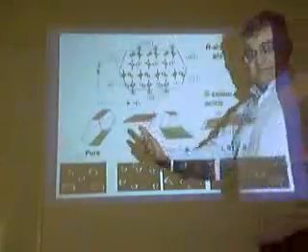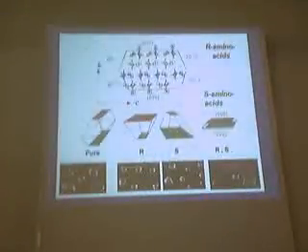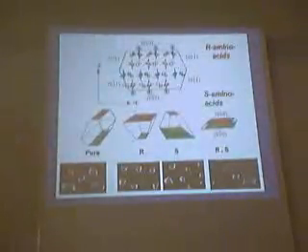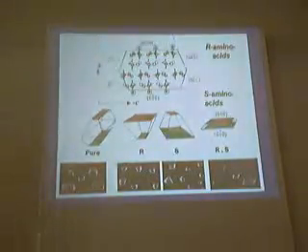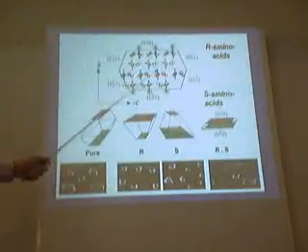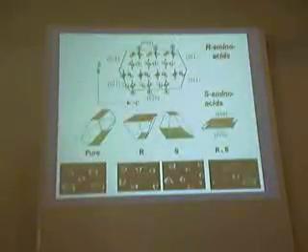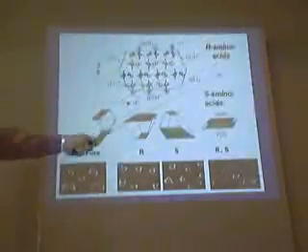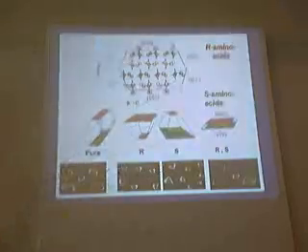And when X-ray started, because of the Friedel law, it was difficult to differentiate between an enantiomorphic L and D, until Bijvoet came in Holland, in 1948, and applied anomalous scattering and was able to tell the absolute configuration. But here, a regular X-ray diffraction method can tell you the absolute sense of chirality of the two surfaces, and therefore these morphological changes can tell us the absolute sense of chirality of the R and S amino acid just by measuring the morphologies of these crystals.